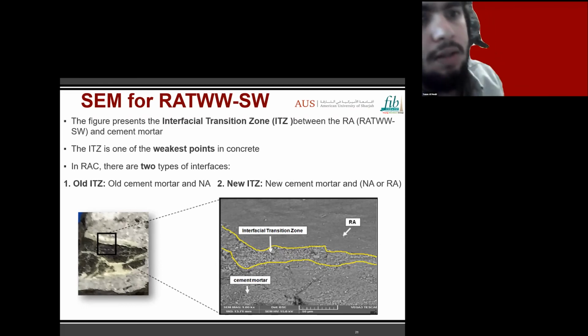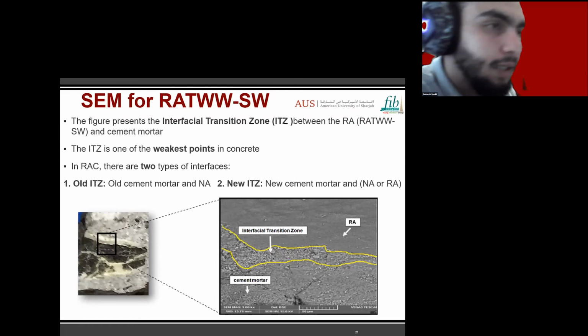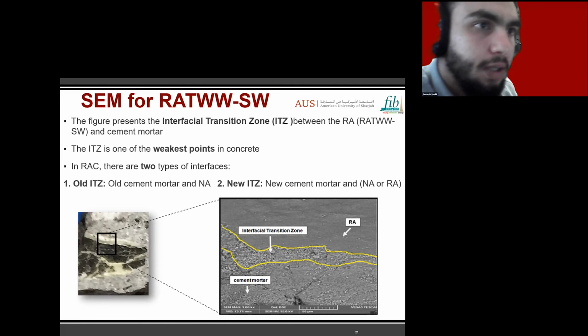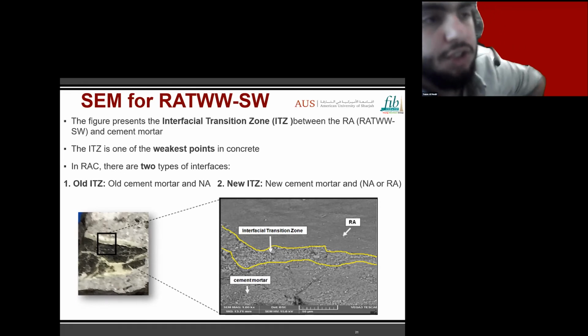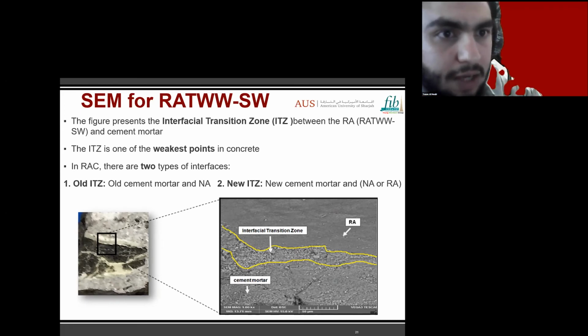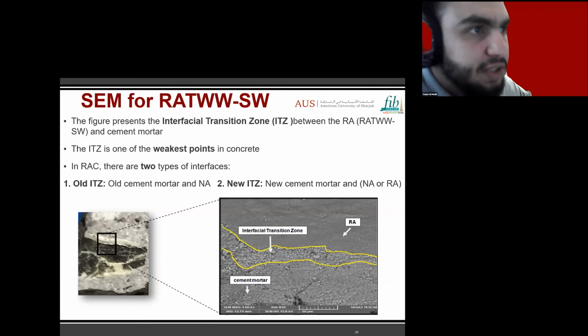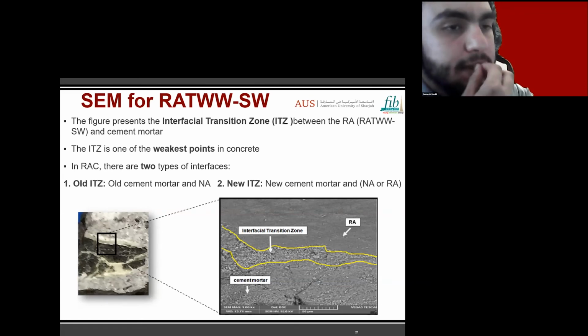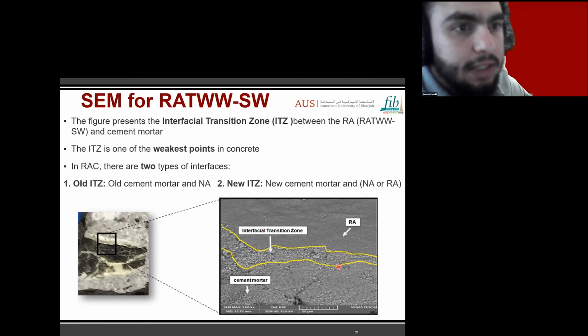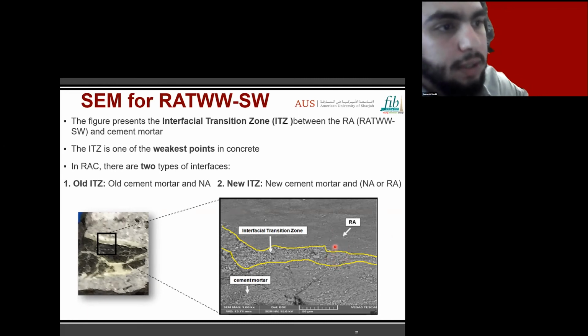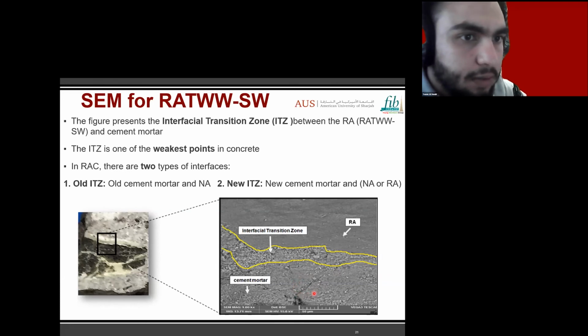In this slide, I shared the ITZ of the RATWW-SW, which is the recycled aggregate mixed with treated wastewater and exposed to salt water. And this corresponds to the most harsh condition and mix. The interfacial transition zone can be observed to have a layer of high porosity between the aggregate and surrounding cement paste, as you can see in this region. And this indicates a weak bonding between the aggregate and the cement and the wall effect. It can also be seen over here, the presence of cracks in the cement paste.